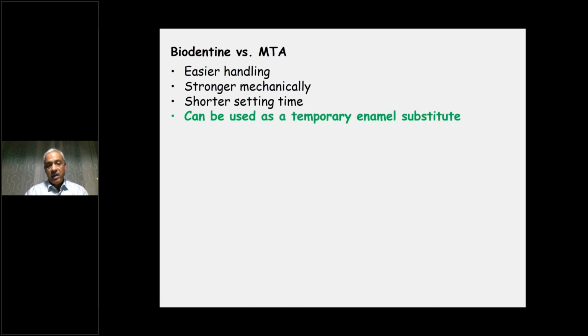And at this time point, I have to tell you that the biggest study that was done on the use of this material as enamel substitute was published in Clinical Investigation. It was done in Marseille. And it was a high number of cases where biodentine was used as a bulk restorative material, and in function of time, a superficial erosion occurred. So the material was reshaped and a resin was applied on it. And that study demonstrated that biodentine can be used, of course, as a permanent dentin substitute, but it could also be used as a temporary enamel substitute for up to 6 months.